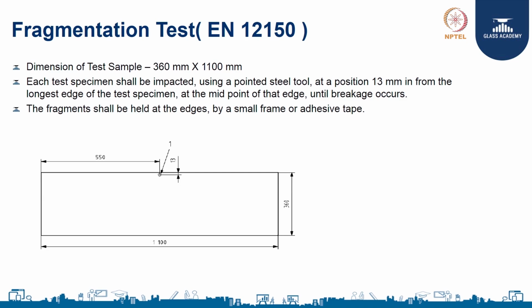What we have to do is break the glass at the center of the 1100 mm side. From the center you have to come at a 13 millimeter distance, and then break the glass with the help of a small tool.